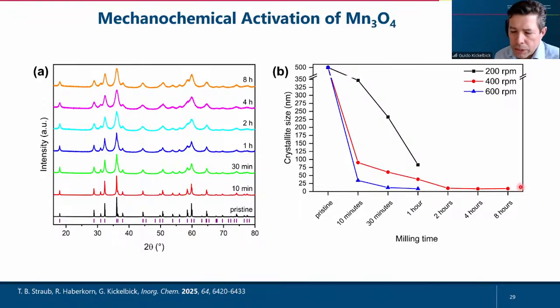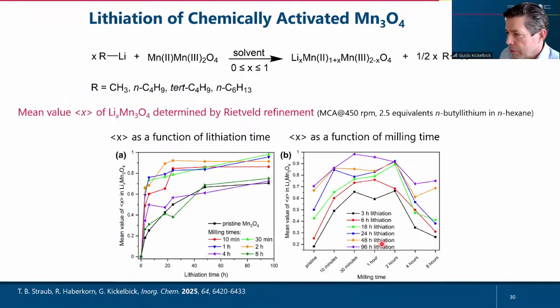And we think there are two reasons for that. One is that you have this crystallite size reduction, and the crystallite size reduction leads to shorter distances for lithium intercalation. And the other reason is that you have also amorphization, a formation of more defects, which probably help during lithium intercalation. And again, this is a very similar result. We published that last year.